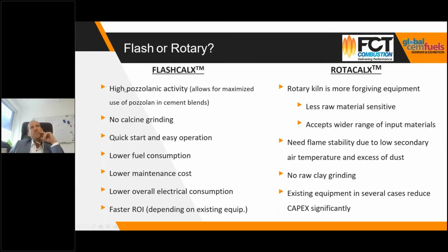So when we are speaking about flash calciner, because of the very good control of temperature that we have, the particles are very fine, and the temperature can be controlled in a very narrow range. So in general terms, you can have a higher reactivity of the clay simply because you can control the temperature better. So you don't need to grind the final product, but you grind the raw material. You can start very easily because of the low quantity of refractories, so you don't need to heat the system for such a long time as a rotary kiln.